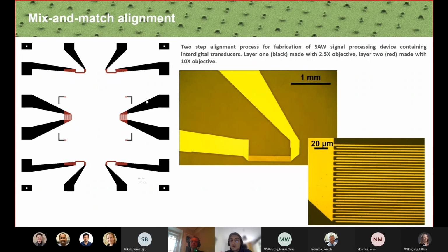But you can also do mix and match with the same machine, which means that you can use two different objectives from SmartPrint. This is a typical example of what you can do. Here in black, you have the first layer fabricated using the 2.5x objective, because it contains the lowest resolution pattern, the contact pads. In the second step, the customer used the 10x objective to fabricate this red layer, which contains 6 different interdigitated electrodes, as you can see here on the right side. By doing alignment and exposure with the 10x, they can contact both layers, the 2.5x objective layer and the 10x objective layer. And so you get the results here, and here the inset. This is what I showed you earlier.